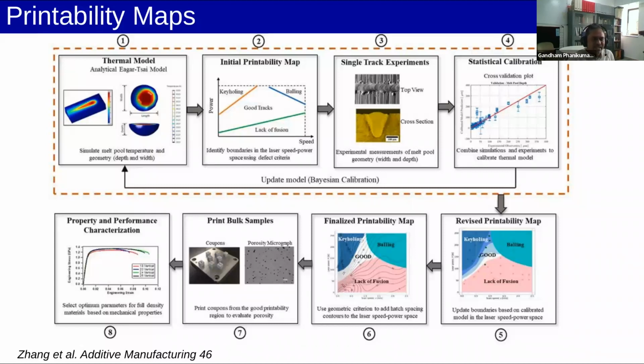So therefore, certain variation is possible, and if you're able to take those variations into account and then calibrate, then you have a fairly good ability to get tracks which are defect free. And then you can also go on to get the map and identify the condition, go on to print, and then test it so that you can actually get the good properties. So there is a scheme of moving forward that is today possible, such that without too many experiments, with a limited set of calibration experiments, you can actually do these.